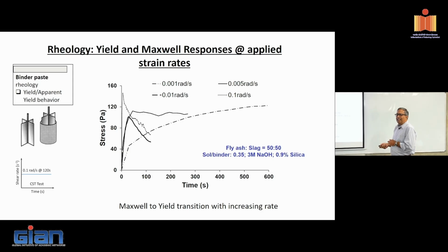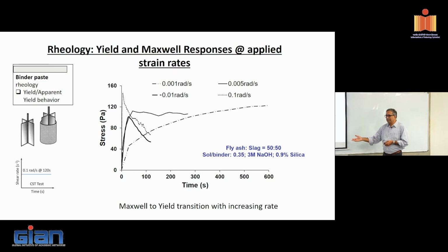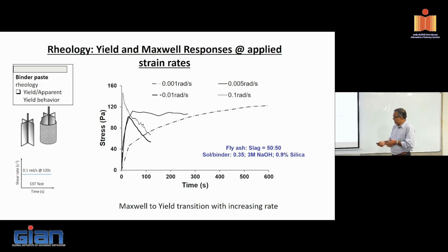Okay, why is that happening? So what is the fundamental difference between these three curves? It's the rate at which I'm loading, right? Which means the viscous solution that I'm dealing with, the activating solution, dominates. It tells me how it is going to deform. If I load it fast, I'll get a yield type response. If I load it slowly, I'll get a Maxwell type response. This is more like a Maxwell type response. What happens in a Maxwell type response? It will continue to deform.